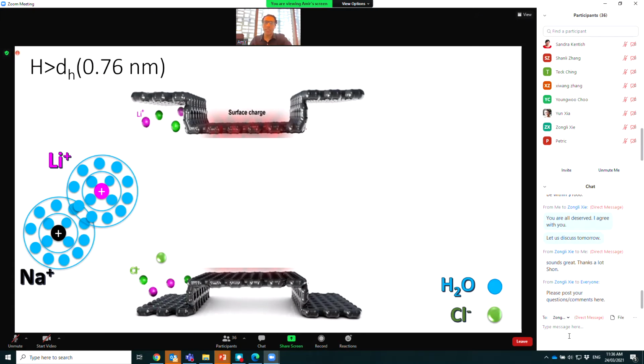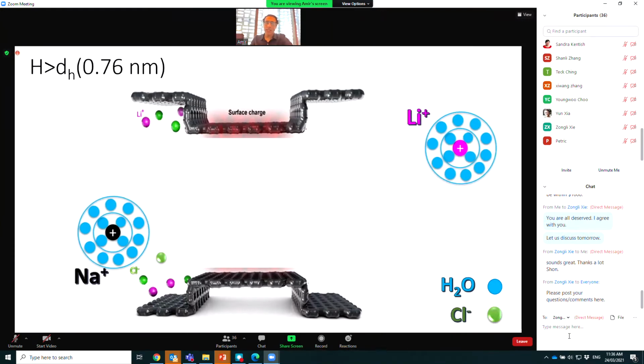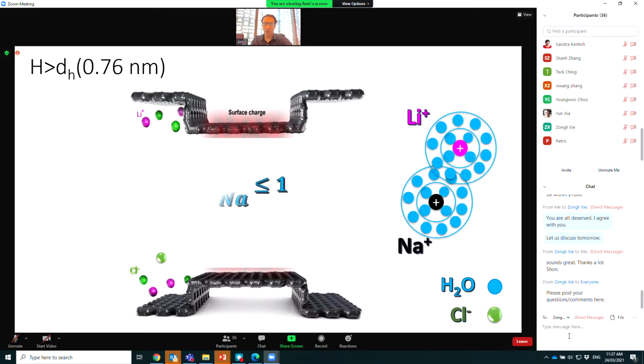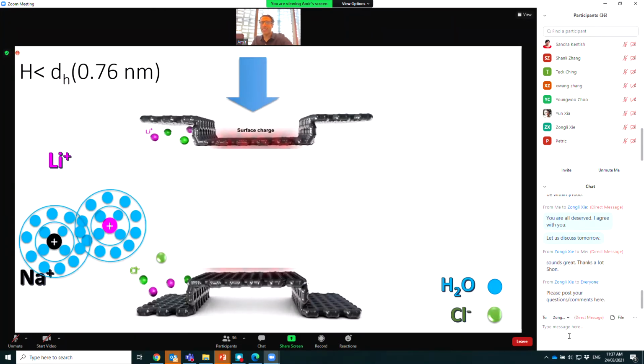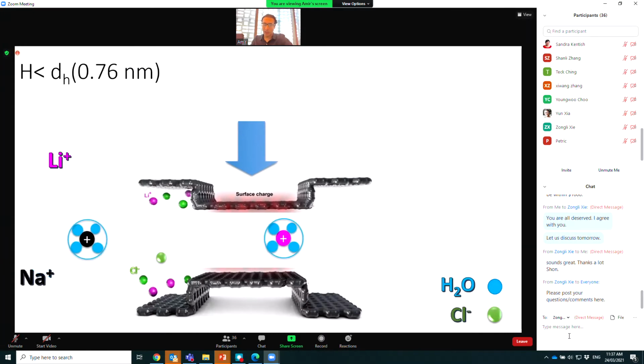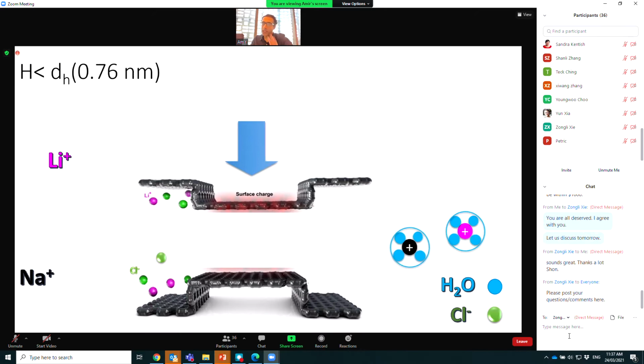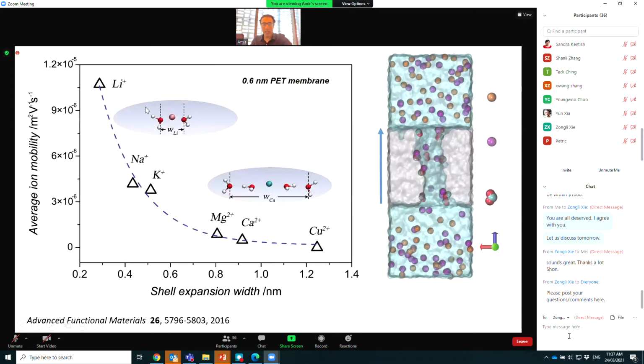lithium ions, 0.76 nanometer. When the size is above the hydration diameter of the lithium ion, the other ions can go through the channel without any selectivity, so your membrane doesn't show selectivity. Whereas when you reduce the size to below 0.76 nanometer, the membrane shows a sort of lithium ion selectivity, and there are many reasons behind this. There are many unknown questions. Something that is currently reported in the literature is that below 0.76 nanometer, the lithium ion shows more ion mobility than other ions, and that also occurs because of the compact shell of the ions within the nanochannel.